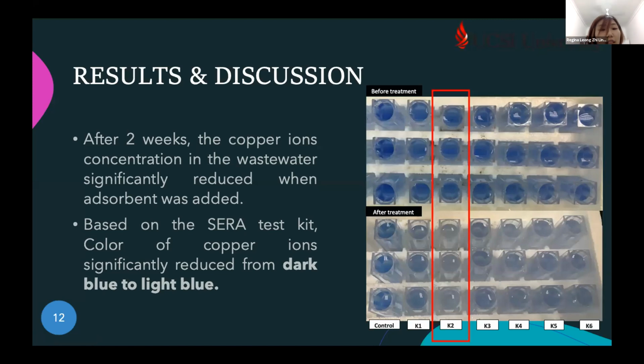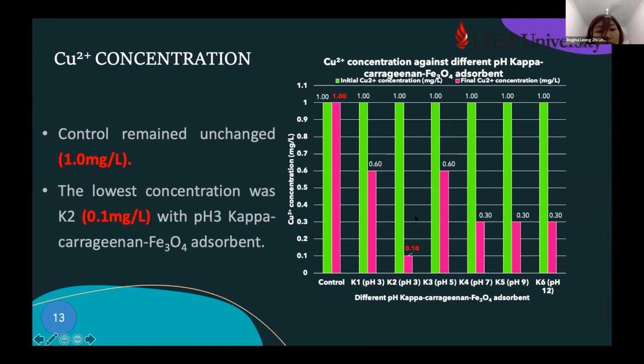So after testing for 2 weeks, the copper concentration in the wastewater significantly reduced when the adsorbent was added. We can see from the figure on the right, the color of the copper ion reduced from dark blue to light blue for each different pH of the adsorbent added, but the control without the adsorbent remained unchanged. From the figure, we can see K2 with pH 3, the color was the lightest in the treatment. The comparison between initial and final copper concentration can also be observed from the graph. K2 with pH 3 showed the lowest copper ion concentration after treatment with only 0.1 milligram per liter, and the control treatment without the adsorbent remained unchanged, which is 1 milligram per liter.